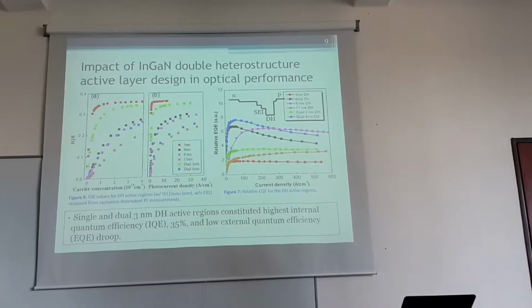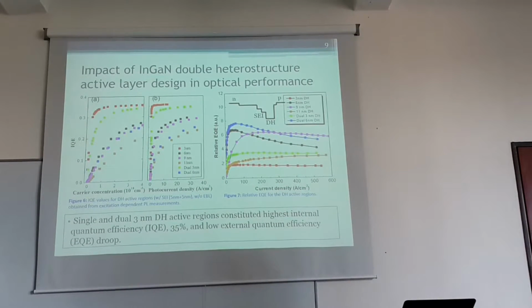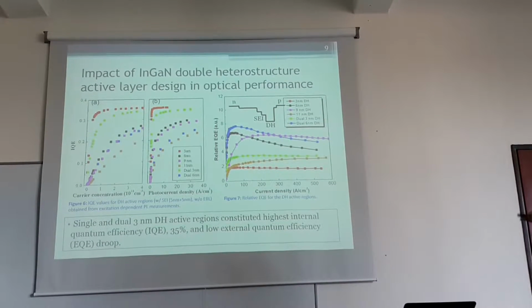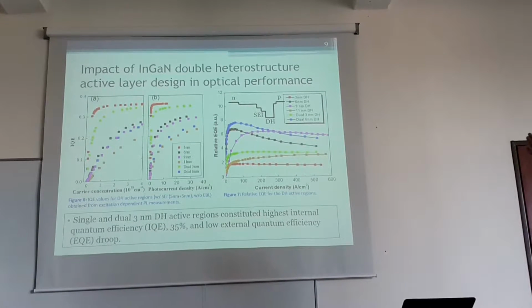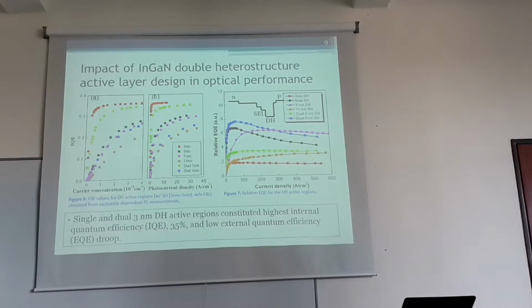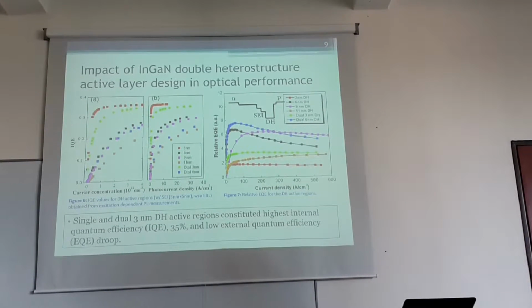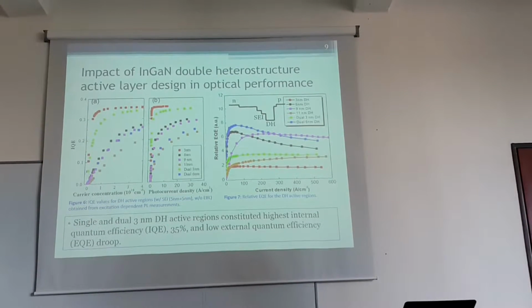These measurements are obtained using temperature dependent photoluminescence measurements and excitation density dependent photoluminescence measurements. The maximum levels are obtained by comparing the 15K and room temperature levels, and the internal quantum efficiency is obtained using excitation dependent measurements.